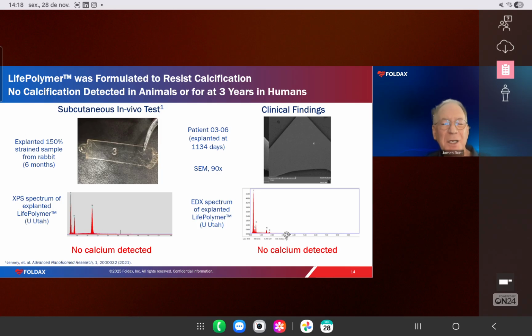Then we use a slightly different characterization technique, energy dispersive X-ray spectroscopy, to again do elemental composition. And again, there's no calcium. So we're getting no calcification in the usual type of in vivo tests. And by the way, if we're interested in all this, in very small font at the bottom left is a paper that we published back in 2021, and it has all these details in there.